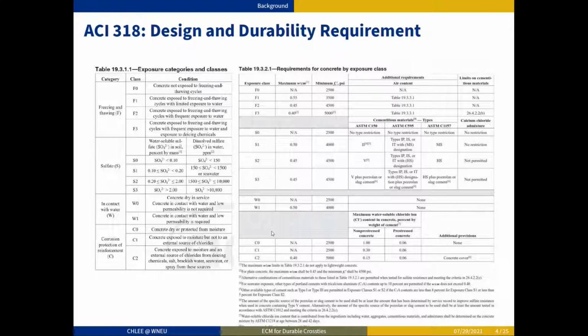However, an interesting point is that if you take a look at the very bottom, maximum water cement ratio of 0.4 and the minimum strength requirement of 5,000 psi, if you satisfy those two conditions, that particular mixture will satisfy any kind of the durability conditions as well.